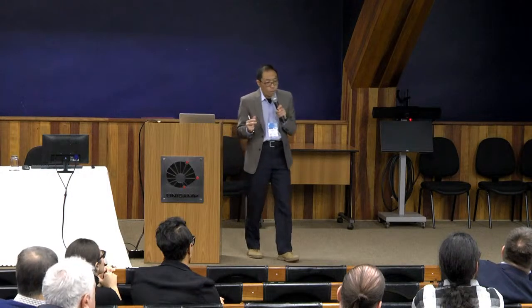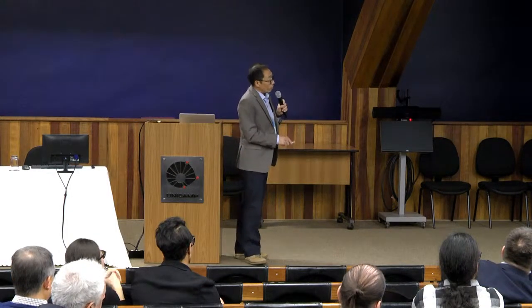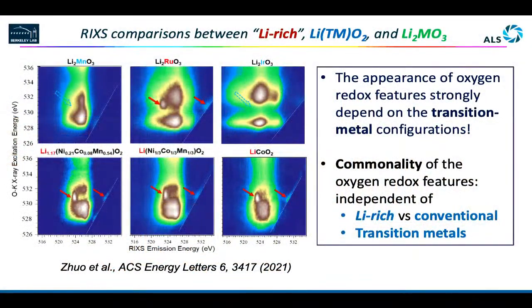So of course the question is where the oxygen redox comes from. And then if we look at the lithium-rich, and if we look at the lithium-1, this is a conventional compound with the nickel cobalt manganese, they show the same behavior when you pull it up to the high voltage. And this is lithium cobalt oxide. If I have time, I will jump to the lithium cobalt oxide at the end a little bit. So they all show up. So they don't really need the lithium-rich configuration. This lithium-rich is really not a requirement in the lithium battery cell. And the other thing is we measured nickel, cobalt, and various kind of compounds. Fundamentally, there's no limitation on where you are expecting this kind of oxygen redox, because fundamentally, they behave all the same.